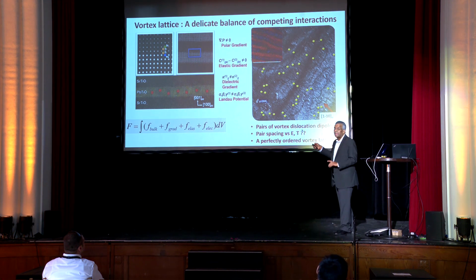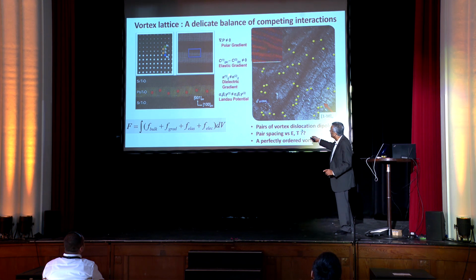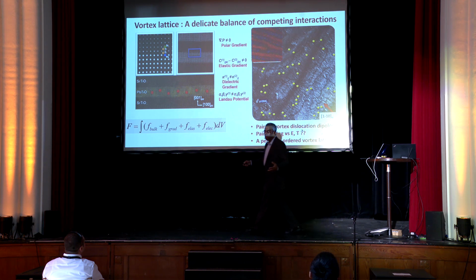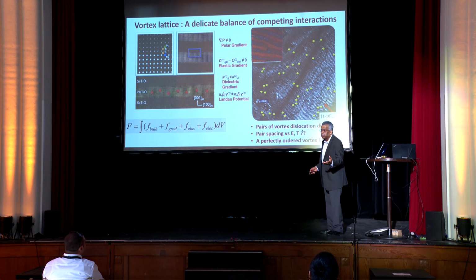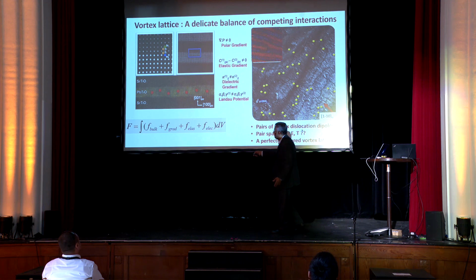Now, with epitaxy, what you can do is to impose polar gradients, like in lead titanate, strontium titanate, elastic gradients, dielectric gradients, and so on. So you now have a framework, a pathway by which you can create a lot of new structures. You can take other such systems like bismuth ferrite or any other ferroelectric or any other material, start to create these emergent textures. Now, the physics is embedded here. If you look at the Hamiltonian for this, there are two terms, the elastic energy and the electrostatic energy. I'm going to spend just 10 seconds explaining that to you.